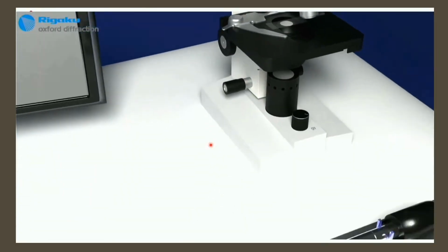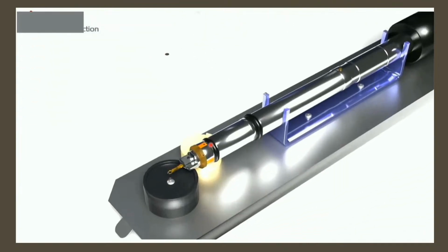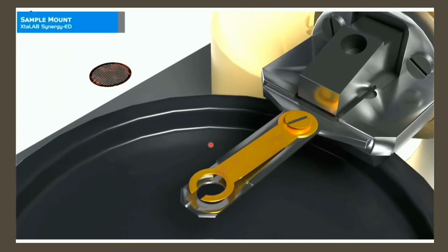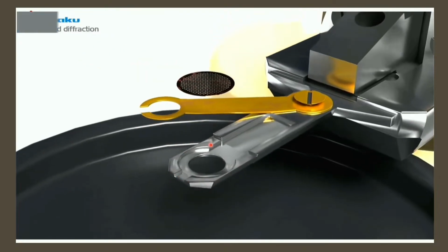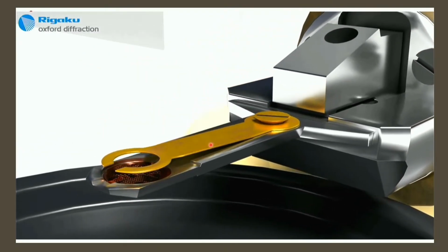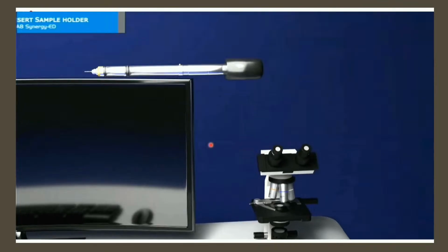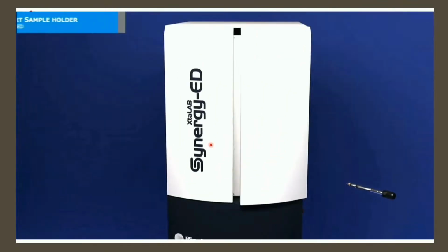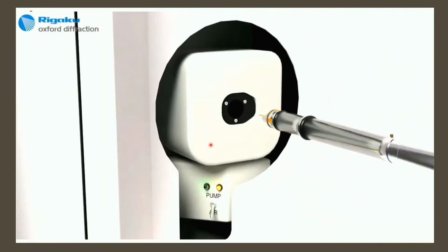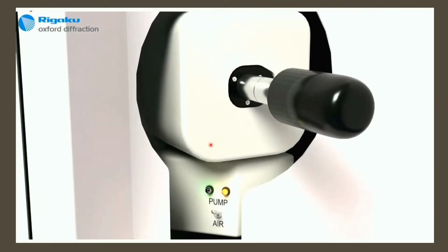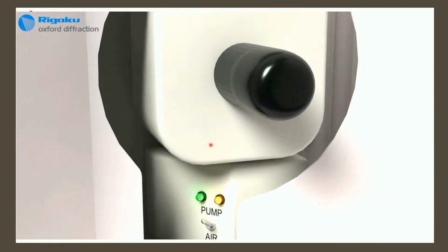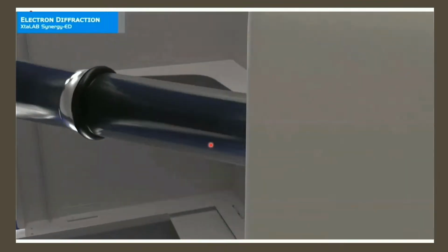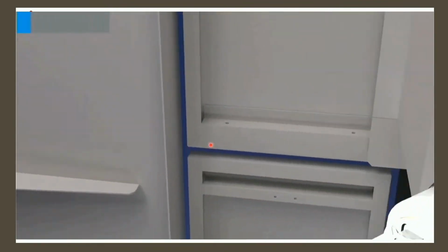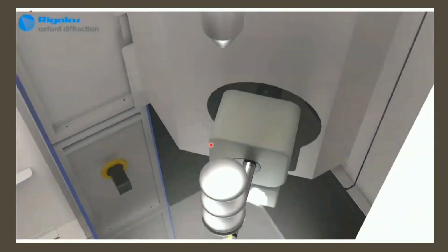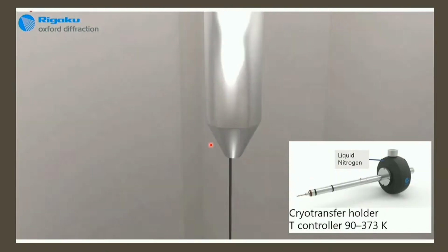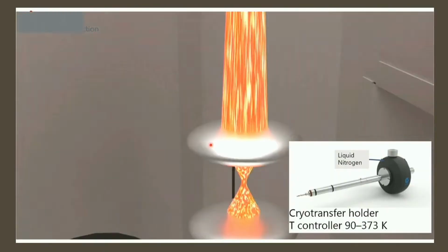Things must be very fast because the electron beam is very high energy, so many materials suffer strong beam damage when exposed to the beam, so we have to be able to collect meaningful data before the crystal is too damaged. And another thing is that, as we said, the instrument is high vacuum, so this can also alter our structure or cause some damage, but we can mitigate this by, for example, cooling down the sample.